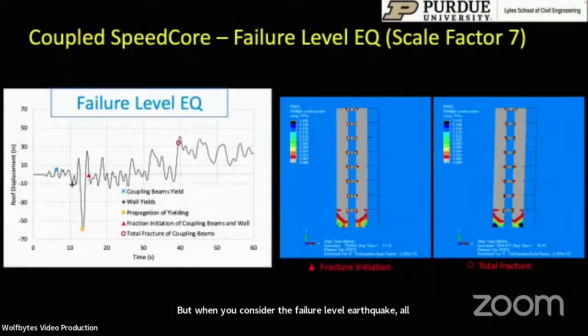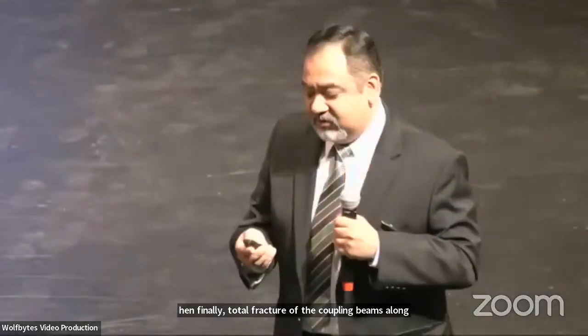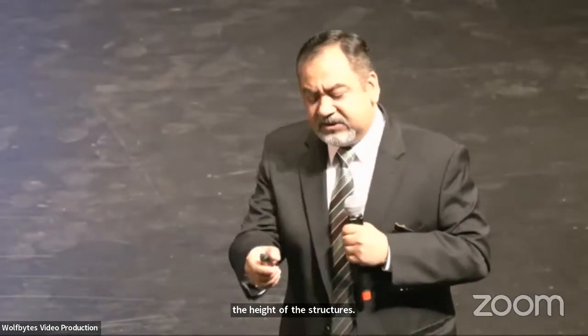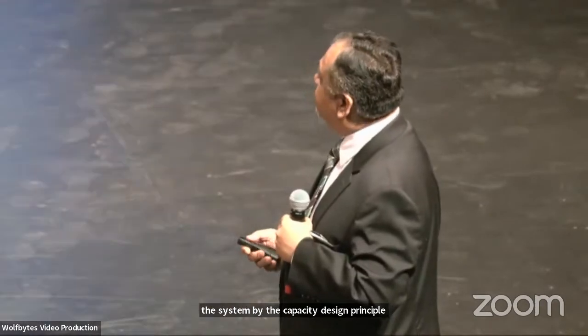You get yielding of the coupling beams, followed by wall yielding, propagation of yielding along the height of the structure, initiation of fracture in the coupling beams, and then finally total fracture of the coupling beams along the height of the structure. So that was the seismic response that was programmed into the system by the capacity design principle, and it gives us exactly that.